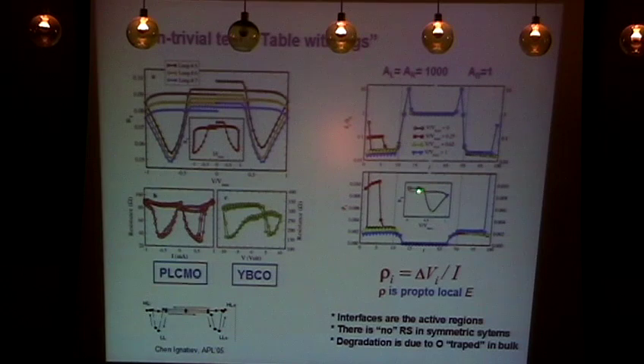So in the second step, the red, all the oxygen vacancies are being pushed across this interface, and eventually they get pushed into the bulk. The moment they go into the bulk, they don't contribute any more to the total resistance, because the parameter A in the bulk is 0. So the interfaces are Schottky barriers, but the bulk is completely regular. So the effect of these vacancies basically vanishes the moment they go into the bulk. That's where you have the green spot there, where you don't have any more accumulation of vacancies either on the left or on the right. So this corresponds to the low resistance state right there, where the densities are minimal.